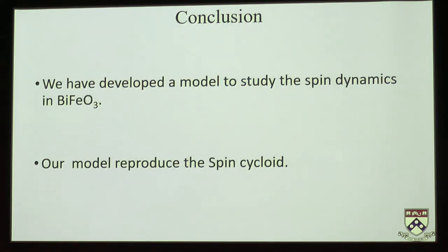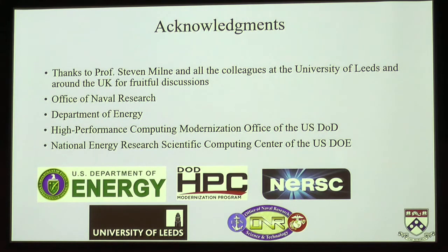So just make a short summary of our magnetic molecular dynamics simulation. We have developed an effective Hamiltonian that describes the spin dynamics and atomic dynamics in bismuth ferrite. And our model can successfully reproduce a spin cycloid observed in experiments.